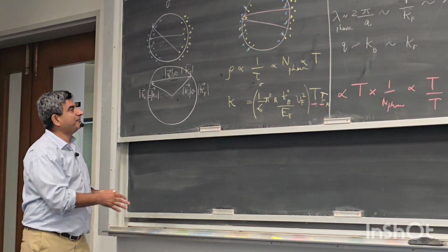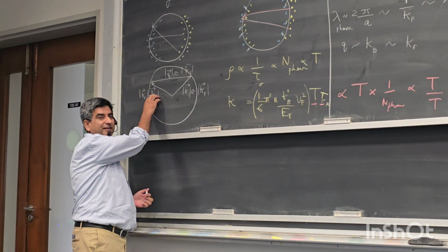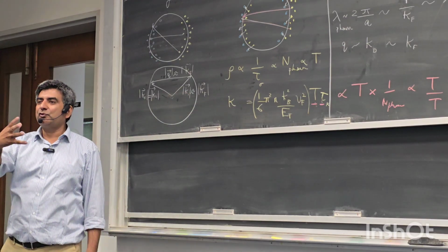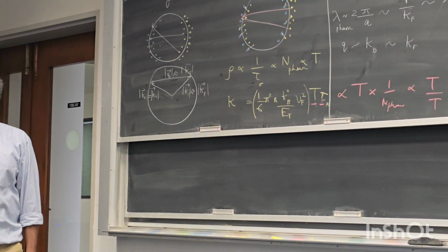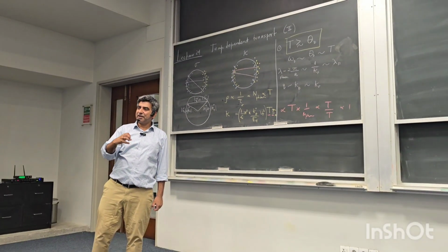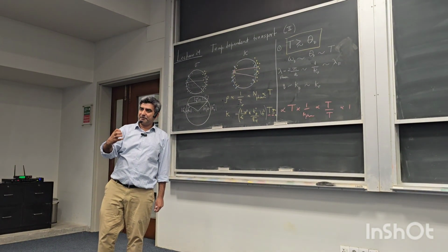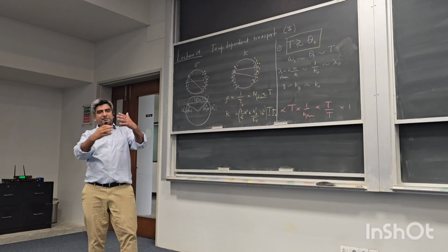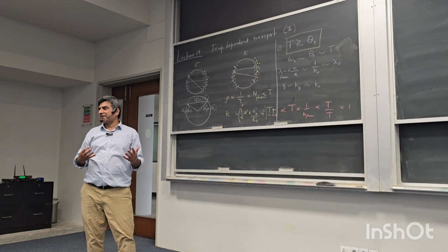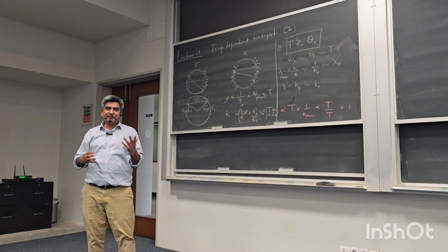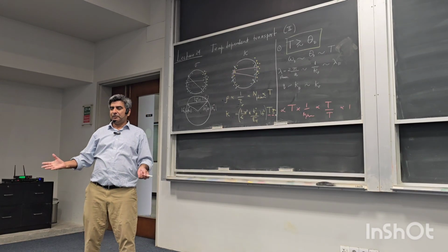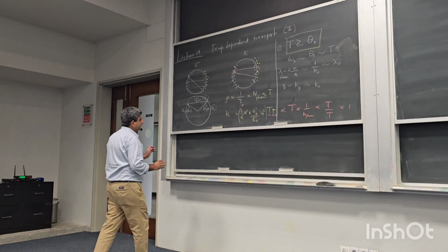It takes more time for an electron to go from the right to the left side. One kick of one phonon absorption emission process does not have that much wave number or that much efficiency to affect this transition from the right to the left side of the Fermi sphere. So one kick is not enough, you need many kicks. Okay, so it becomes a highly inefficient process.